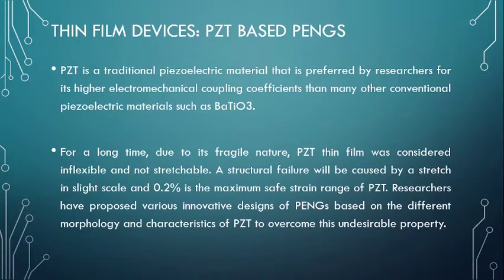Next, we have thin film devices, which are PZT-based PENGs. PZT, or lead zirconate titanate, is a traditional piezoelectric material that is preferred by researchers for its higher electromechanical coupling coefficients than many other conventional piezoelectric materials such as barium titanate. For a long time, due to its fragile nature, PZT thin film was considered inflexible and not stretchable. A structural failure will be caused by a stretch in slight scale, and 0.2% is the maximum safe strain range of PZT. Researchers have proposed various innovative designs of PENGs based on the different morphology and characteristics of PZT to overcome this undesirable property.